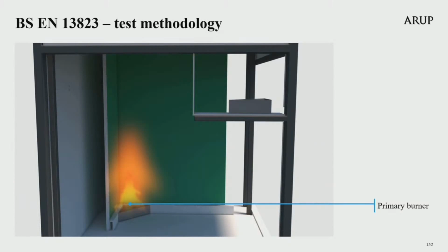The test rig contains 2 burners, a primary burner, as is shown in the diagram, and an auxiliary burner, and I will explain that next. This primary burner is located at the corner of the two wings, offset from the front face by 40 millimetres. It is a triangular tray filled with sand with two equal sides of 250 millimetres and a height of 80 millimetres. A gas pipe is attached to the tray, so the gas flows through the sand, diffusing it. The burner is calibrated to give a heat output of 30.7 kilowatts, which is intended to represent a waste paper bin on fire in the corner of the room.